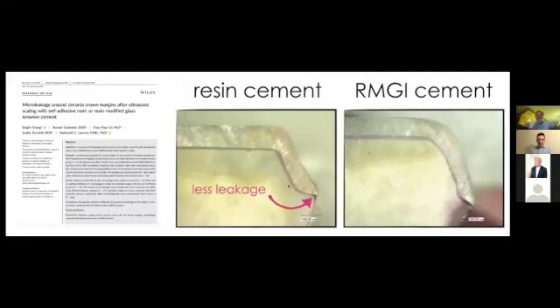And lastly, this last little study shows another advantage of bonding to zirconia: you get less leakage with resin cements than with RMGI cements. This was actually a study done by Ron Goldstein. He had the question of whether using ultrasonic scalers on ceramic crowns would disrupt the cement margin, so we compared and looked at that. I think we found that ultrasonic scaling didn't increase microleakage, but one of the things we incidentally found was a lot less microleakage in crowns cemented with resin cement than those cemented with RMGI cement. So that was another neat advantage of using resin cement to bond zirconia.